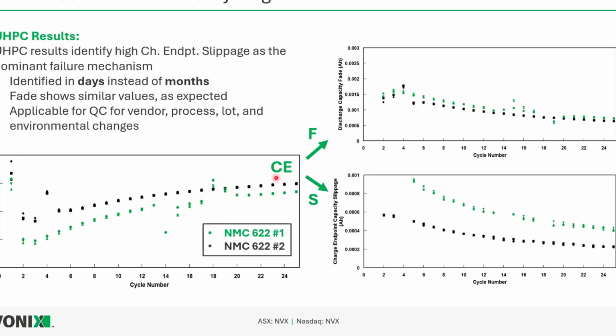When we split CE into our fade component and our slippage component, we can see, as expected, there's almost no difference in capacity fade, which we expect based on the earlier results. But where we see this huge result happening is in charge endpoint capacity slippage. These mechanisms that are donating electrons at the cathode, typically electrolyte oxidation, transition metal dissolution, and this rate is about twice as high as this number 2 batch. So obviously there's something happening here that we can detect just in a few cycles very consistently and accurately.